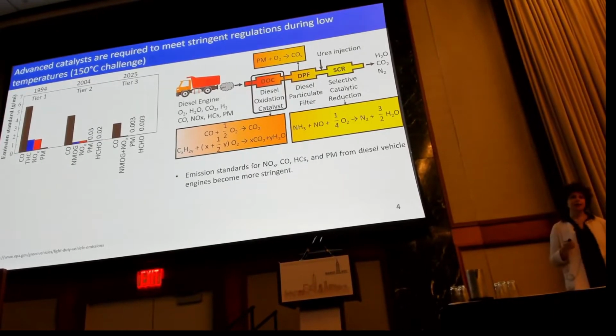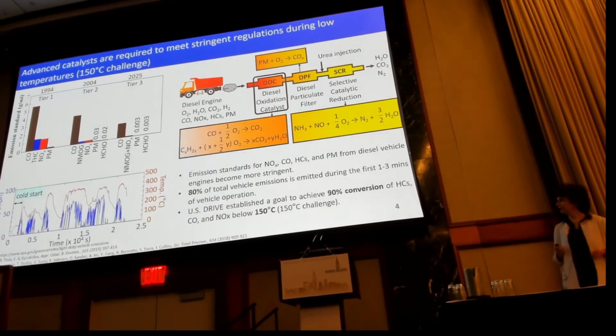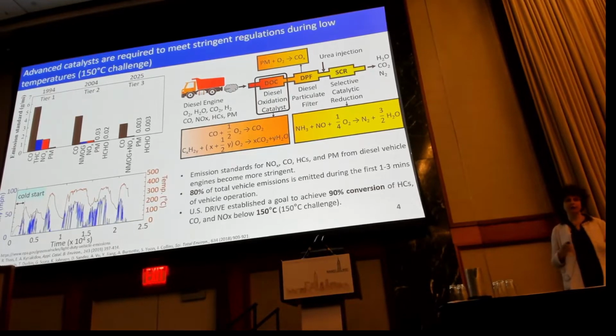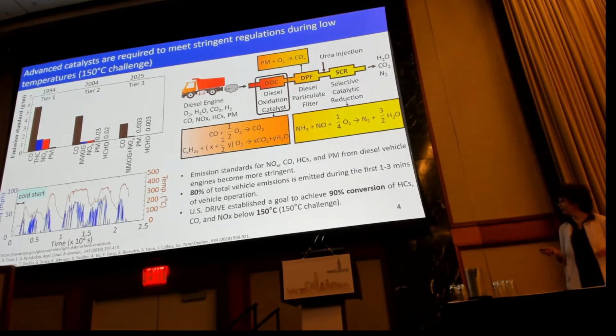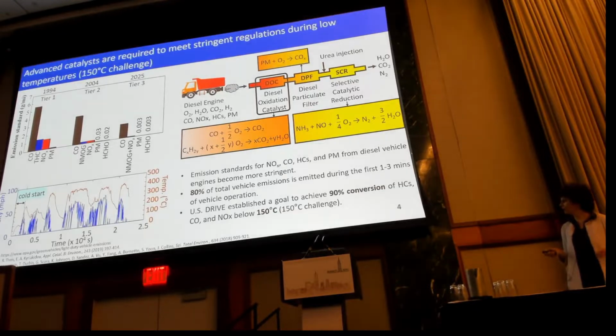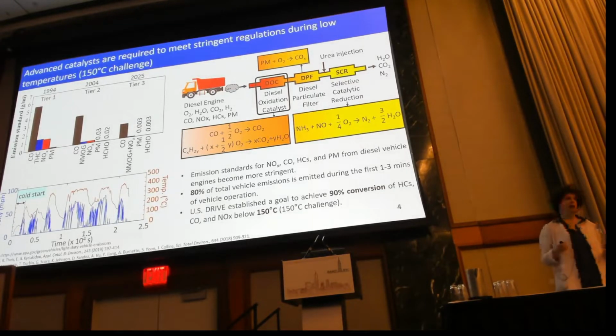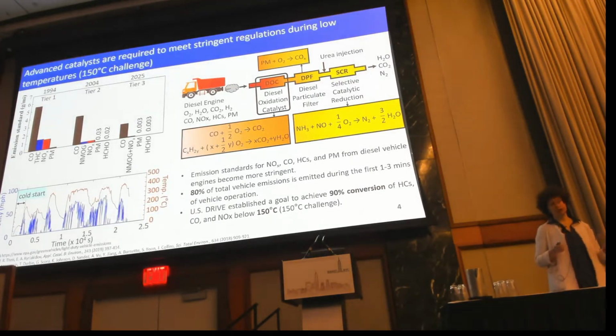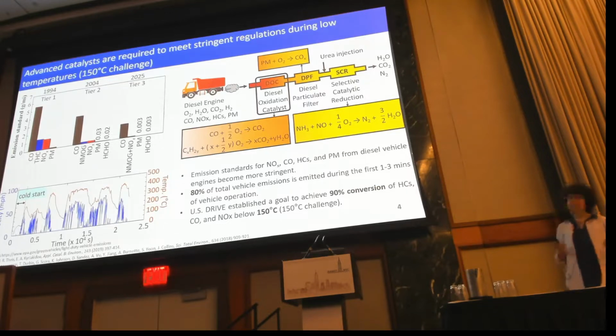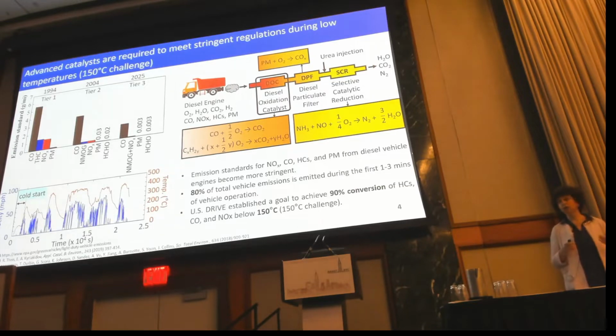So one of the main challenges in diesel vehicles is that the exhaust during the first 1 to 3 minutes of vehicle operation is relatively cold, so we call it a cold start. And within this cold start, almost 80% of the emissions are released into the atmosphere. So the emissions community established a target of achieving 90% conversion of CO, hydrocarbons, and NOx at 150 degrees C, which makes it very challenging to find a catalyst that is active at that low temperature.